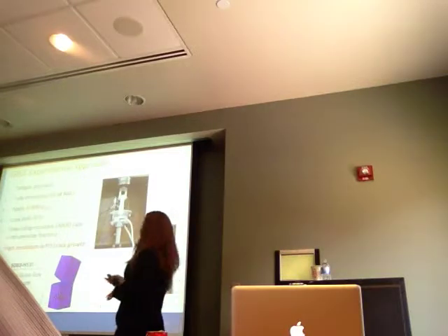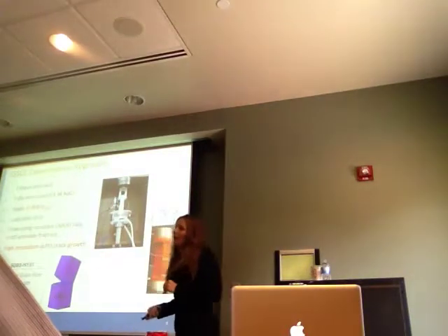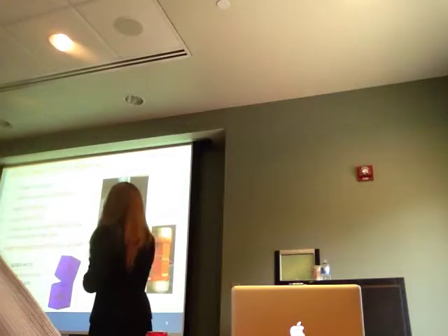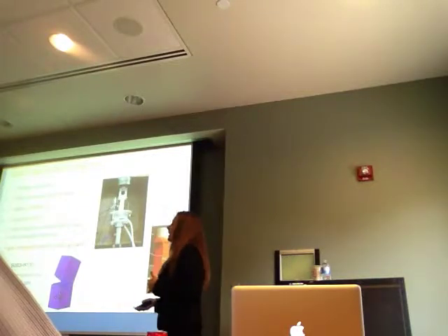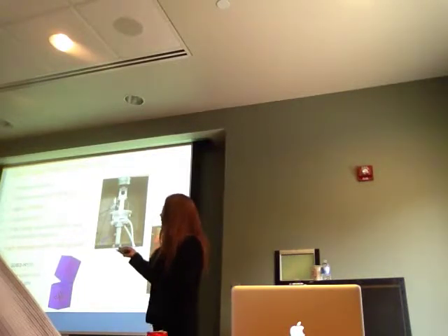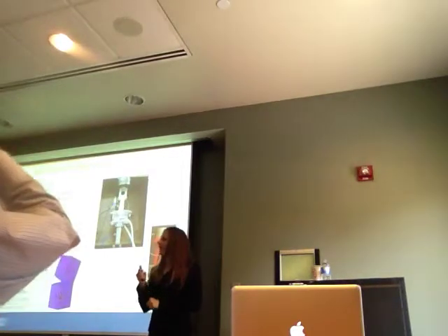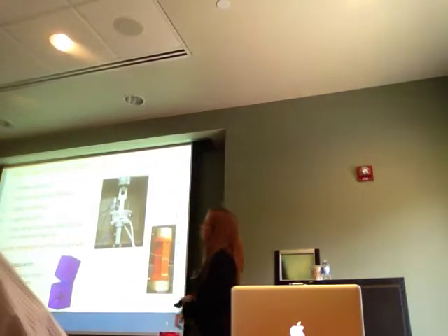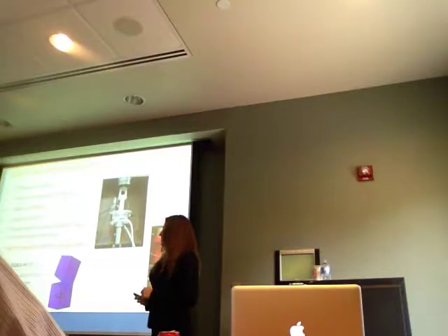Then I put a fatigue pre-crack in air to get a sharp crack tip, loaded the specimen in sodium chloride, and applied a polarization that was near the open circuit potential. And then I loaded it at a very low load for 10 hours to see if I could measure the intergranular corrosion. And then right after 10 hours, I started to increase the displacement rate at a constant rate until the specimen failed. And during this entire time, I was measuring the crack growth rate with a high resolution direct current potential drop method.